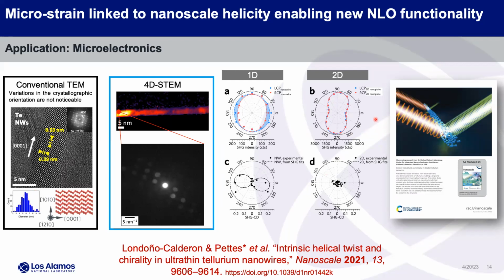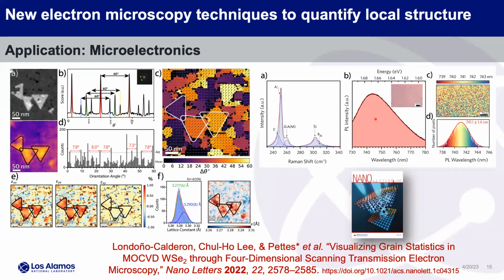This is with second harmonic generation. You have crystals that don't have symmetry, you can do second harmonic generation on them. So this is an SHG circularly polarized light experiment. Then we can do the same kind of work on these grain structures in 2D materials, looking at misorientations, looking at how strain happens in the crystals.